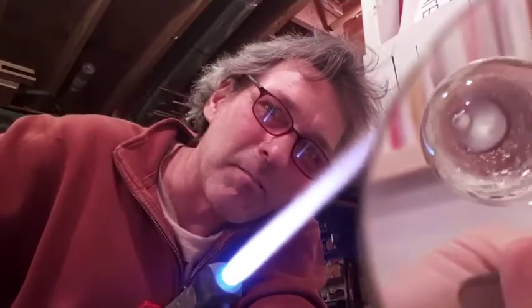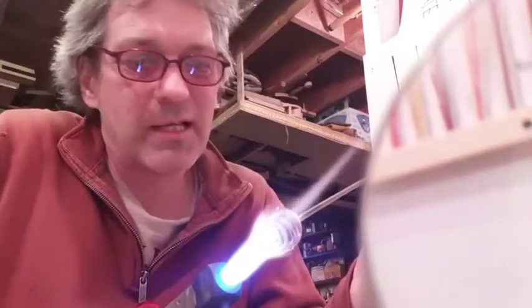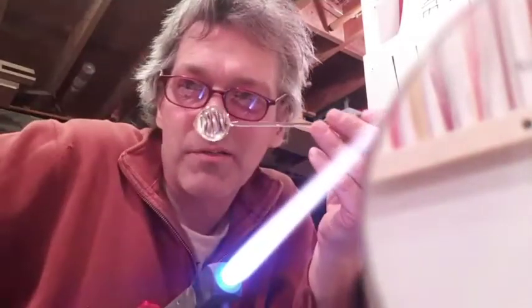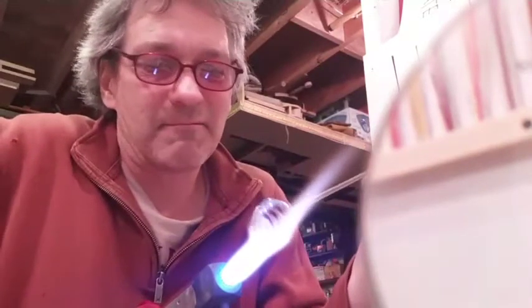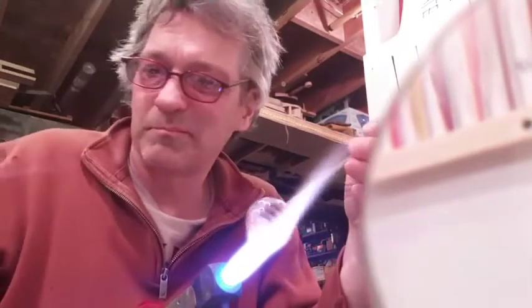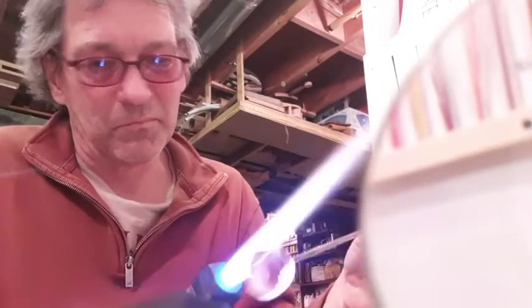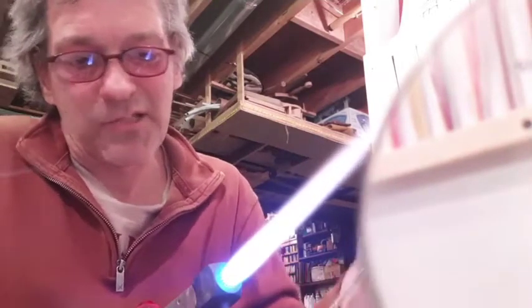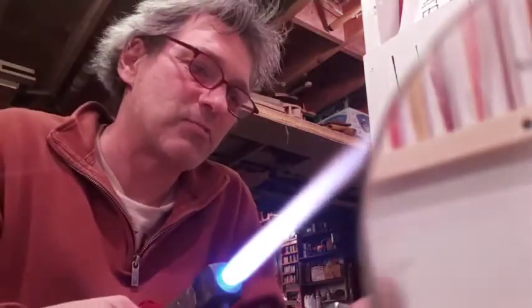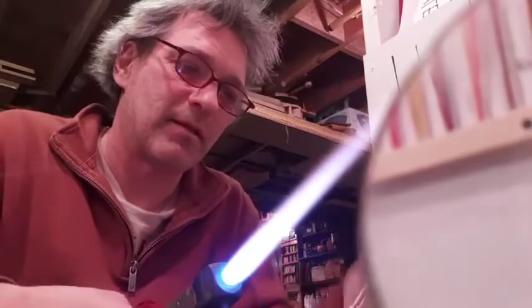You can see the surface. If you see the reflections from the lights above, you can see the little ripples still in that. So let's heat it up. We'll run it through the graphite marble molds and improve the sphericalness of this side. So I'm going to use a marble mold, once again, that's just a little bit bigger than my marble, then go to one that's smaller than the diameter of the marble. Use just the rim of that mold to make it more spherical.